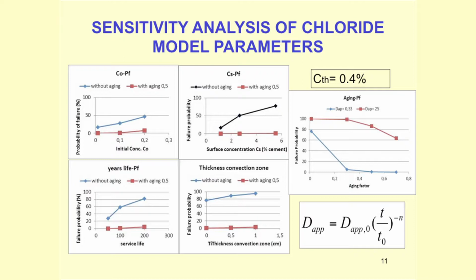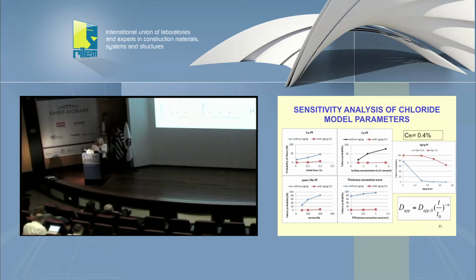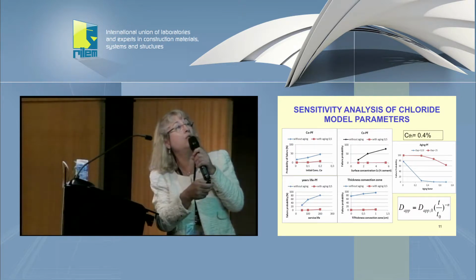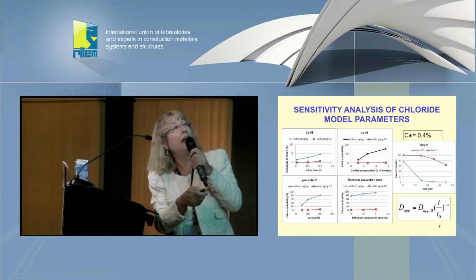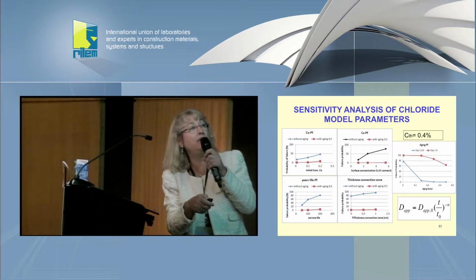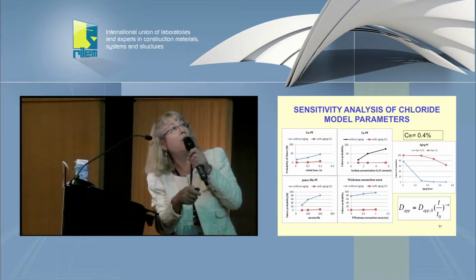There are very, very important differences when we just tune or shift the values. In that case, it's very necessary to say all the numbers assume, otherwise you will have completely different probabilities of failure. With aging, that is the red one, as soon as you have a high aging factor, in Spain is suggested 0.5 for all cases, really the probability of failure is very, very low. That means that the service life of 50 years, I think that I did this with 50 years, will be fulfilled always.